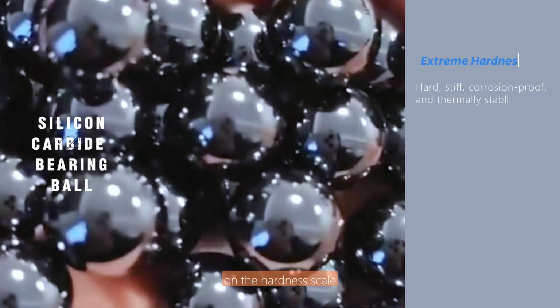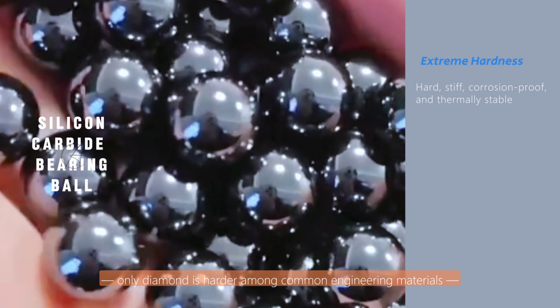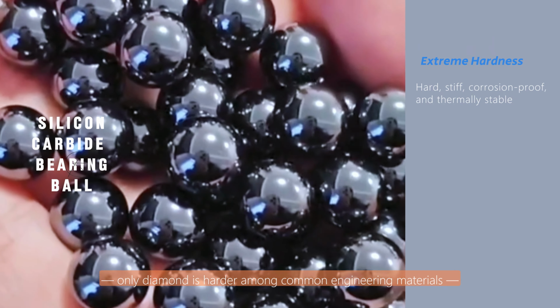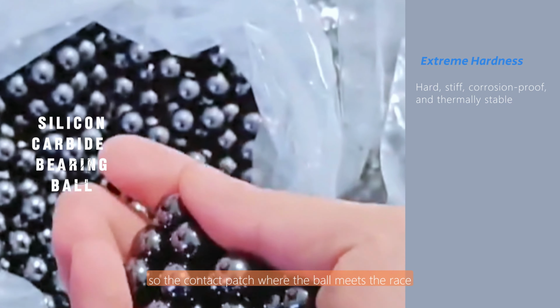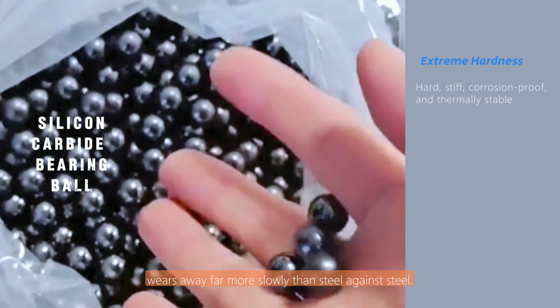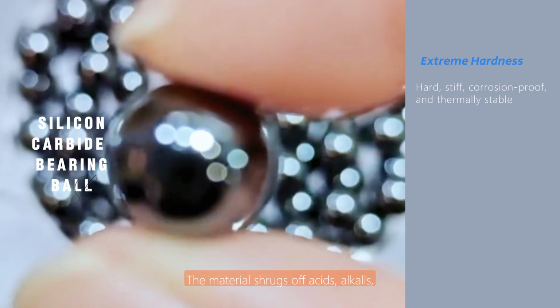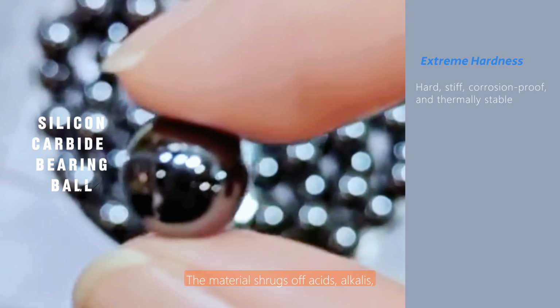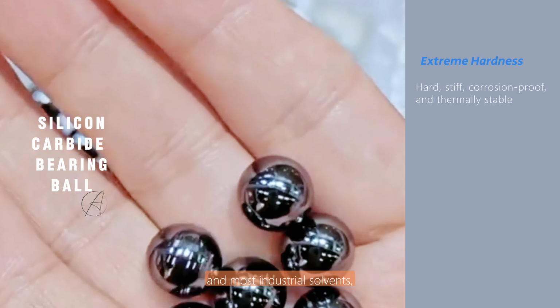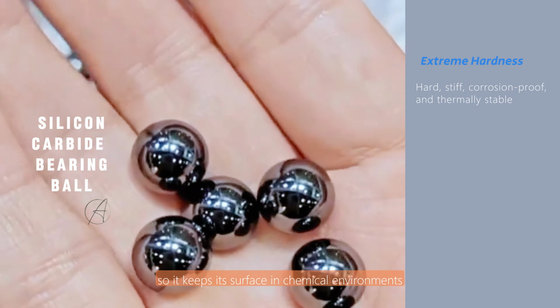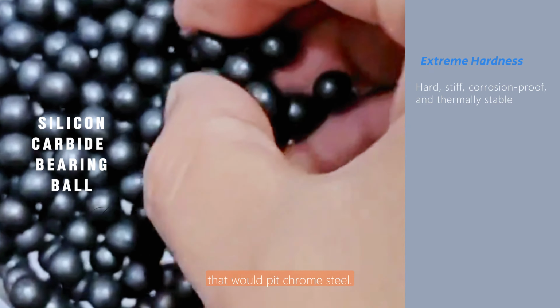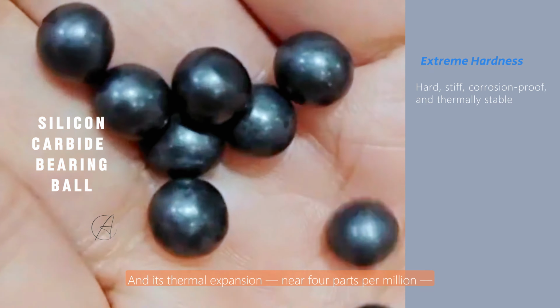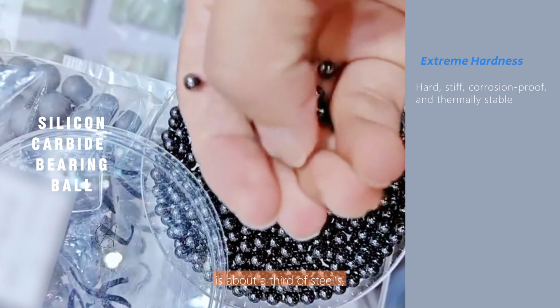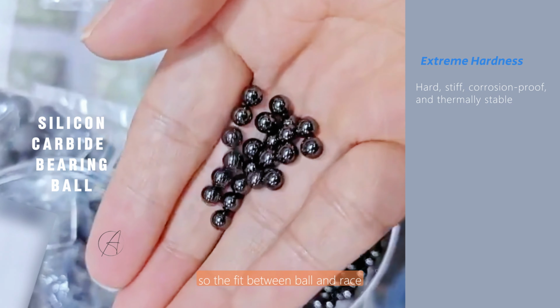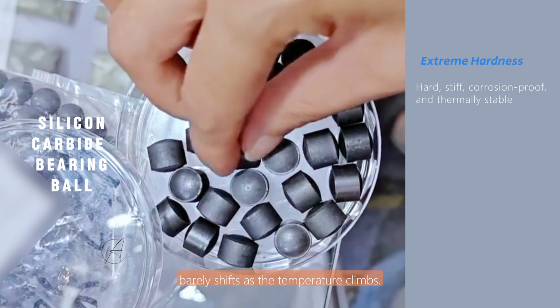Silicon carbide sits at roughly Mohs 9 on the hardness scale. Only diamond is harder among common engineering materials. So the contact patch where the ball meets the race wears away far more slowly than steel against steel. The material shrugs off acids, alkalis, and most industrial solvents, so it keeps its surface in chemical environments that would pit chrome steel. And its thermal expansion, near 4 parts per million, is about a third of steel's, so the fit between ball and race barely shifts as the temperature climbs.